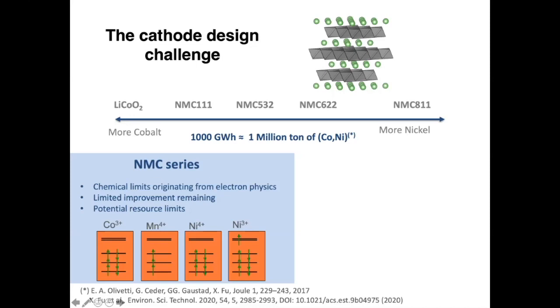And then there is, of course, a potential resource issue. Everybody knows about the cobalt issue, but of course the nickel issue is just as severe. If you want to make a terawatt-hour per year of NMC, then you need 1 million tons of combined cobalt and nickel. And with NMC-811, that's now mostly nickel. And to put that in perspective, that's today 40% of the world production of nickel.